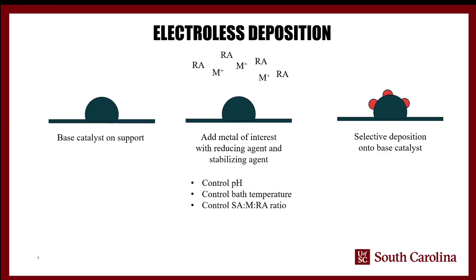More interestingly, they can do it with at least 3 different metals. So they've demonstrated at various points monometallic deposition, so just adding one metal to the substrate, bimetallic deposition, which I'm going to talk about tonight, and they've also demonstrated trimetallic deposition. So they can get particles that by all measurements are truly alloyed for anywhere from 1 to 3 metals. And in theory, as long as you have the syringe pumps and the right ratios, you could even go higher than that. You could do 4, 5, 6 metals all together at the same time. Whether there's any reason to actually do it, it's a whole other story. But the capability is there.